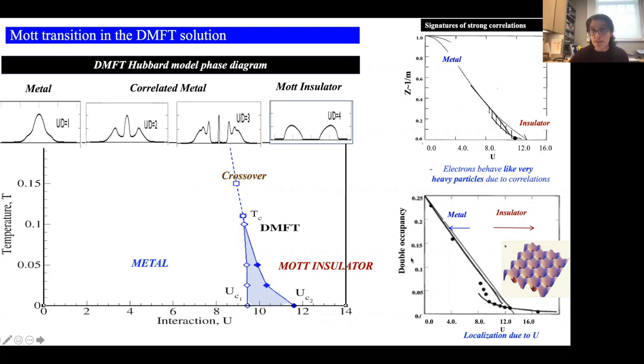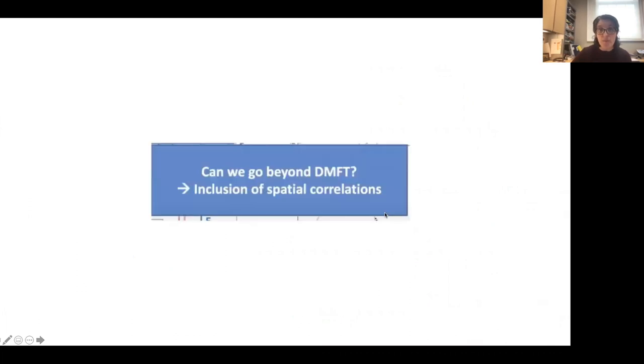Another signature that this is really a correlation-driven phase transition is if you look at double occupancy as a function of U. So as you go to the insulating regime, electrons like to be localized because it costs too much energy to have two electrons in a given site. Okay, so this is a well-known result that has been obtained with dynamical mean field theory.